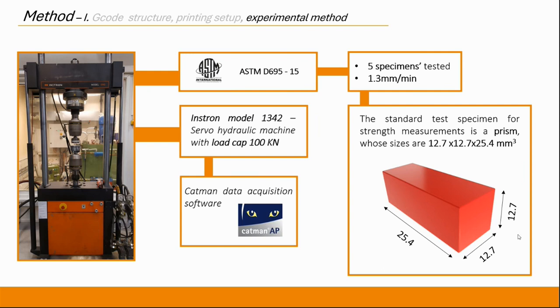As a result, the specimens have a prismatic shape with a length twice its principal width, and the specimen is rotated so that the ±45-degree layers are parallel to the printing plate. The diameter of the PLA filament is 2.85 millimeters, and the nozzle dimension is 0.3 millimeters.